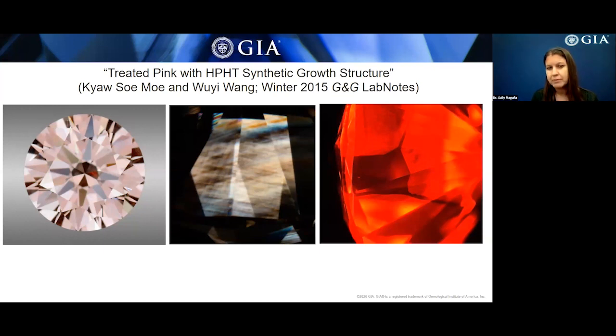Interestingly, diamond view imaging of the stone showed cubo-octahedral growth with dark sectors, which is usually seen in HPHT laboratory grown diamonds. So while the diamond view can generally be very reliable at revealing the growth structure of natural versus laboratory grown diamond, this treated diamond is a good example of why we need to correctly interpret all identifying characteristics.